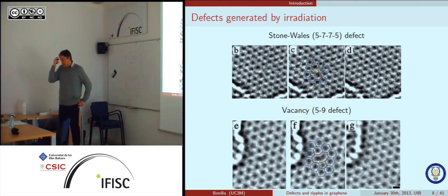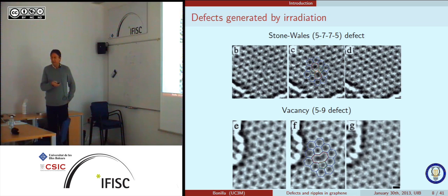Okay, so this is the same work. What they did is irradiate at 80 kilovolts, and every now and then these electrons knock some atoms and switch a bond, and then instead of having hexagons all over the place, you may have this defect, which is called the Stone-Wales defect, because Stone and Wales studied the rotation first. And so you get two heptagons here and two pentagons there. The microscope takes data every 1 or 2 seconds. The difference between these views is a few seconds, I believe 4 seconds or something like that. It turns out that this defect disappears after 4 seconds in those experiments.